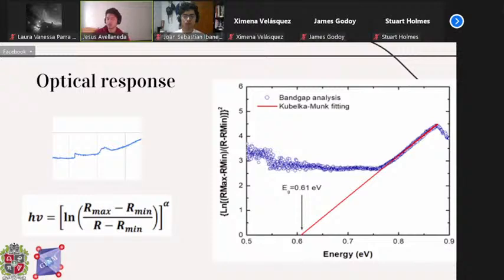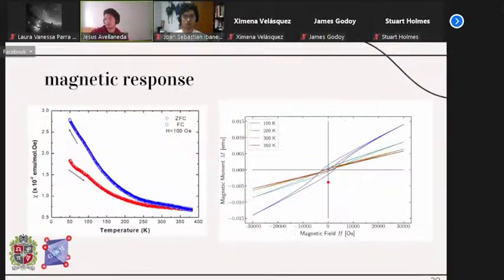In addition, when we apply the Kubelka-Munk method and adjust the linear part of the data, it gives us an optical band gap of 0.61 electron volts. So in a first approximation, this will place the material as a semiconductor with a band gap near other materials known in literature, such as germanium or silicon, if I'm not mistaken. So that was all about the optical response.